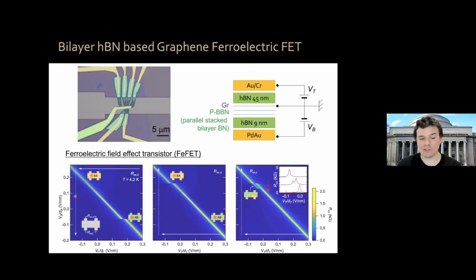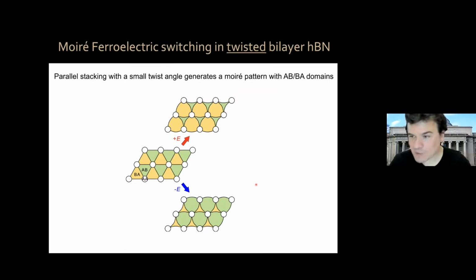We can do this continuously as a function of back gate and top gate. We can see how we go from having BA stacking configuration abruptly to AB stacking. And if we reverse, we go from AB stacking to BA stacking at a different electric field. Sometimes we actually catch it as a domain wall motion is sweeping through our contacts, so that we have these two states, given by two domains in some regions. Yeah. Now, that was for exact 0 degree stacking.